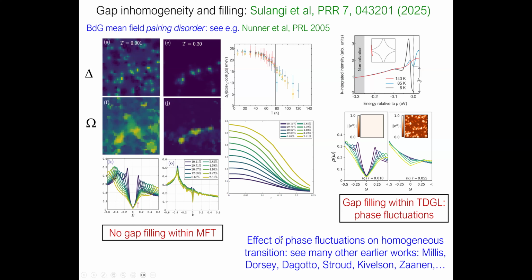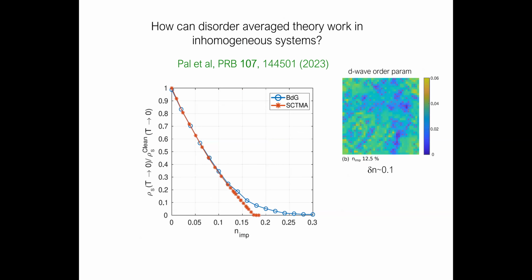And so we turn to an explanation, which has actually been around also for quite a while, which is that phase fluctuations can fill in the gap. These are a lot of works from a lot of different people who worked primarily on homogeneous systems. And here we've combined those phase fluctuations in a time-dependent Ginzburg-Landau approach with disorder to show that the same thing happens. It's not particularly surprising. So the message is that if you would like to understand the physics of this transition, you need very strong variations in the local pairing interactions due to disorder, and you need phase fluctuations. Okay, I think that I've gone through that already.